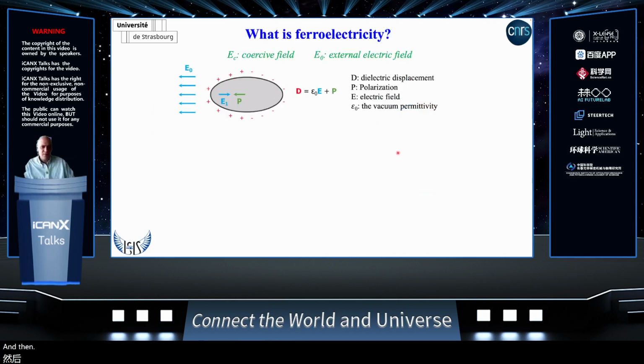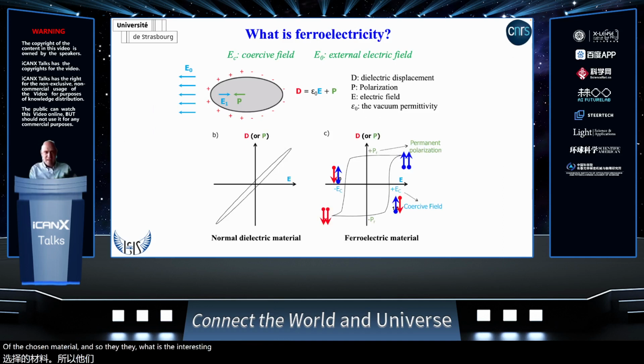And so, of course, most of you, if not all of you, know what ferroelectricity is. It is obtained if you apply a voltage that exceeds the coercive field. The dipoles of the ferroelectric material partially align with the electric field, and this results in a permanent polarization even when you remove the applied electric field. So the magnitude of the polarization will depend on the difference between the external electric field that you apply and the coercive field of the chosen material. What is interesting is that, depending on the field that you apply, you can access intermediate polarization states, and this is, of course, very interesting for application in multilevel memories.